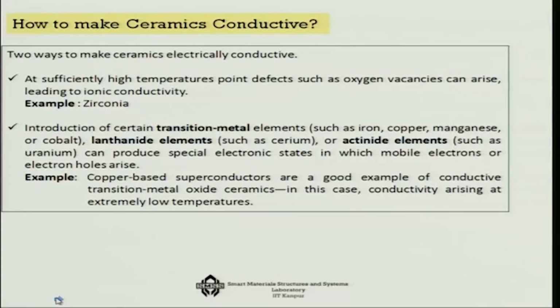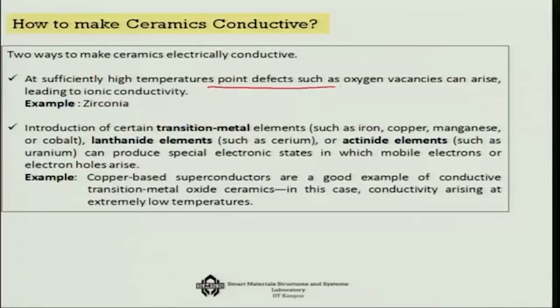Now, how do we make ceramics conductive, because ceramics are generally insulating in nature. There are two ways in which we can make the ceramics electrically conductive. One is that you raise the temperature, because at sufficiently high temperature point defects such as oxygen vacancies can arise, and this will lead to ionic conductivity. That is something that happens in zirconia. The other is to introduce transition metal elements such as iron, copper, manganese or cobalt, or lanthanide elements such as cerium, or actinide elements such as uranium. If you use these, it can produce a special electronic state in which the mobile electrons or electron holes will increase.